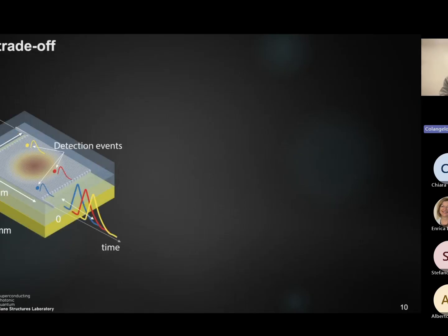And here, to show you the trade-off, we take a 20 micron by 20 micron area detector, and we try to make a very large detector because we want to maximize the collection efficiency. So we want to have a very high efficiency. And this detector is actually referenced to a gold ground plane because it's embedded in an optical cavity. Now, we assume that our projected fiber spot generates 3 hotspots, so we have 3 photon detections, and we can see that one is very close to the ground, while one is very close to the readout.